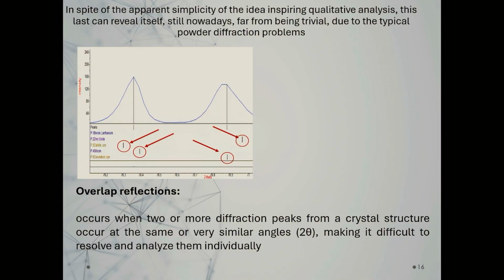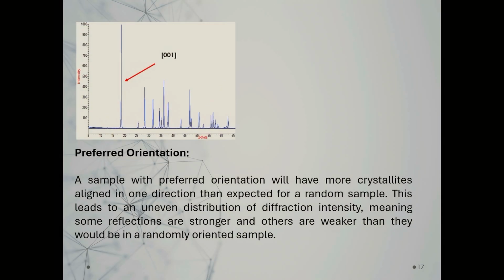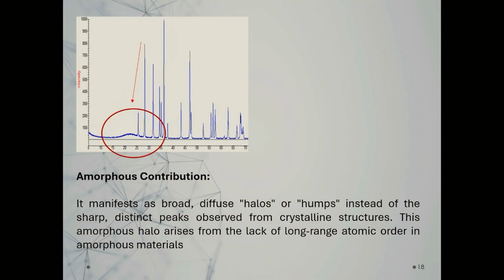As we will see here, we have a huge number of problems that can affect our pattern. This is the case of overlapping reflections, when we have two or more peaks under only one peak. Another problem is preferred orientation. A sample with a preferred orientation has a lot of crystallites that are preferentially oriented. This causes, of course, an error when we calculate the intensity, because some peaks are more intense. Another problem is the amorphous contribution.